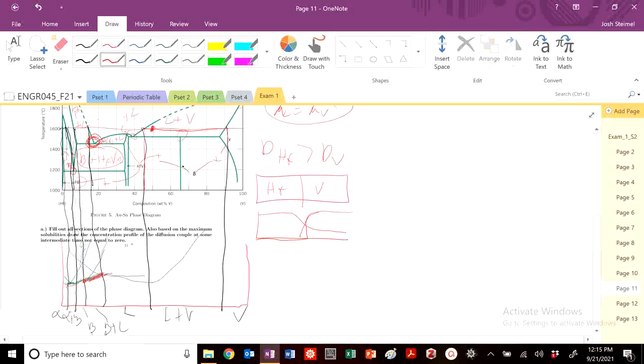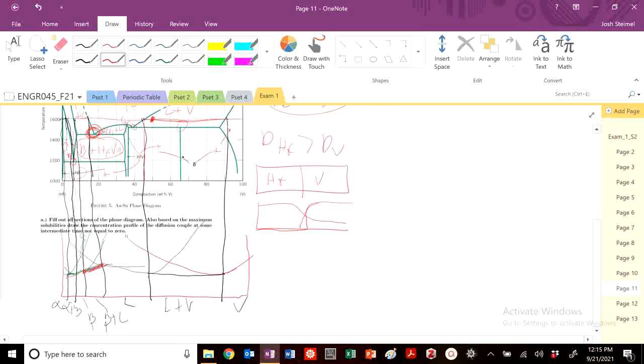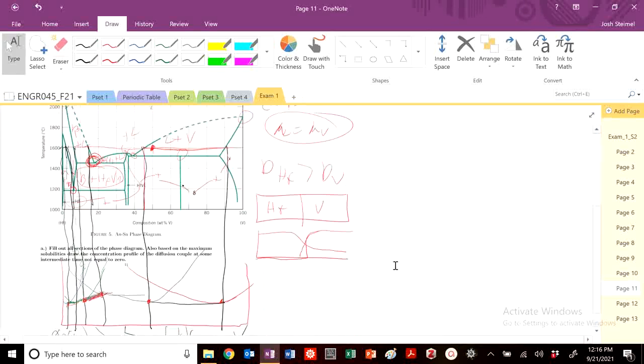And then let me draw my red line. Again, I could draw my common tangent between here and here. A common tangent line. And then vanadium is my last phase. The key idea is, again, I have a common tangent between the slopes whenever I'm in these two-phase regions. Common tangent, common tangent, common tangent, common tangent. That's it. In a single-phase region, you see which curve is the lowest, and that's all there is to it. So that would be my free energy curve.